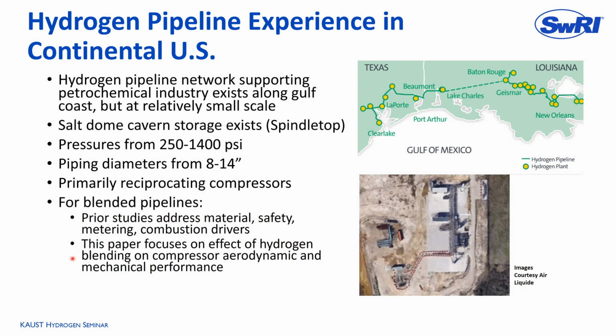So the pipeline operates at pressures ranging between 250 and 1400 psi. It's relatively small compared to a natural gas pipeline, at least the larger pipelines, so 8 to 14 inches. Larger natural gas pipelines are going over 40 inches in diameter, so moving a lot more energy. At the relatively small scale that these pipelines operate at, they're typically driven by reciprocating compressors. So there is a lot of experience there.